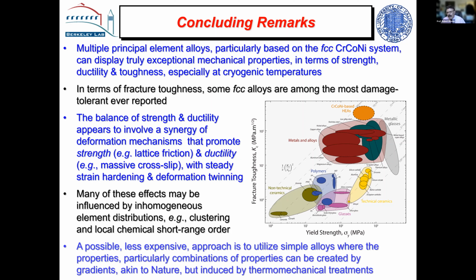It's a question of proving it, of course, but there are differences here, and so things we take for granted, like just twinning formation, may not be quite the same in these materials when you have this array of elements. And how much local ordering affects that, no one knows, but you can see how it might, right? That's another tantalizing concept to think about. Anyway, currently the short range order community in the high entropy alloys either thinks it accounts for everything, or it doesn't exist and accounts for nothing. And I think both those opinions are wrong, but somewhere in the middle is what's actually happening. Yeah, intriguing.